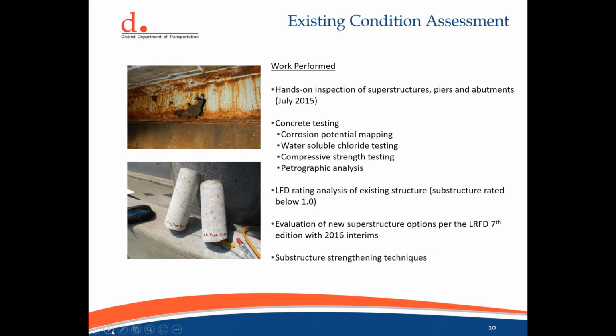So we went out and did a hands-on inspection in 2015 to corroborate the biennial inspection findings. And during the inspection, part of it was we took cores of the existing deck and substructure, and we tested those for chlorides. And the samples did come back with deeper chloride penetration than what is recommended. We also did a petrographic analysis, or a test, and the bond of the cement paste was compromised, and the depth of the carbonation was excessive.